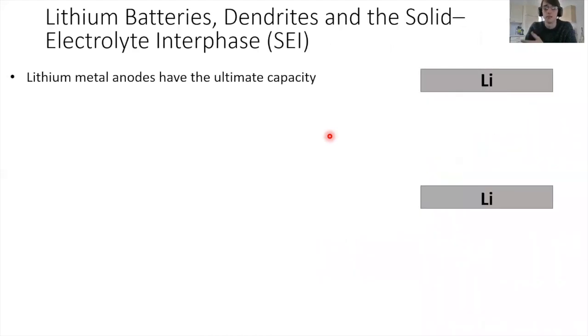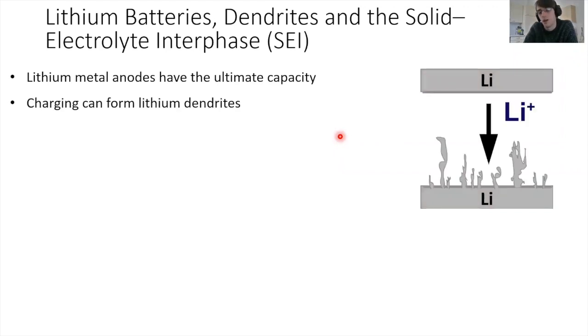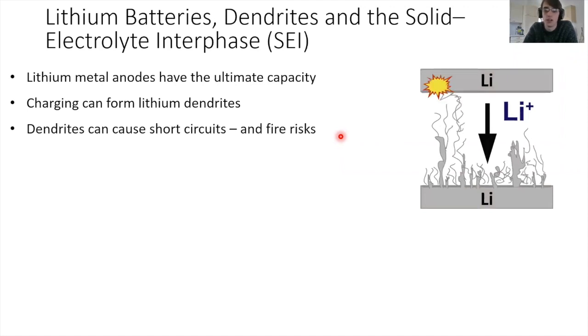Okay, so this is all well and good, so reviving 70-year-old science, but we wanted to do something different with it. We were looking at, this is a battery group from Cambridge, so we were looking at lithium metal batteries, and these could have higher energy densities than traditional graphite anodes, but the trouble is that they form dendrites. These are sort of microstructures that can grow across and then short circuit your cell and set it on fire, which is not ideal.